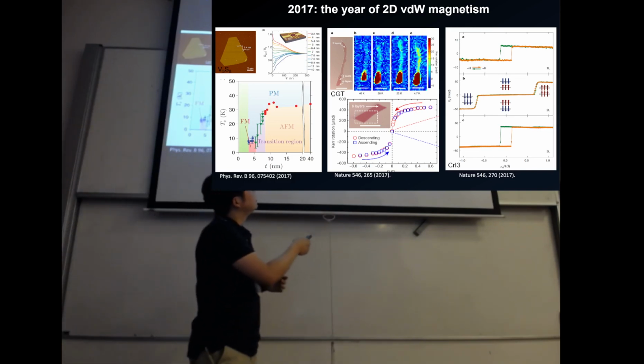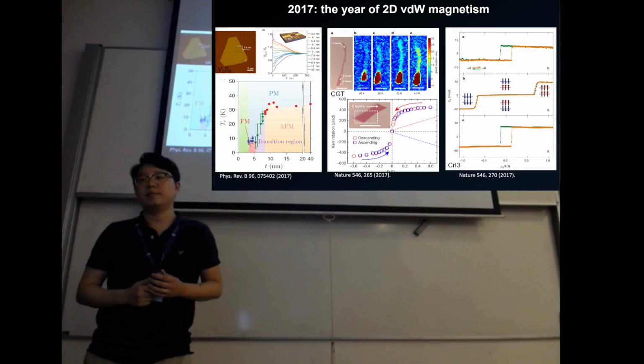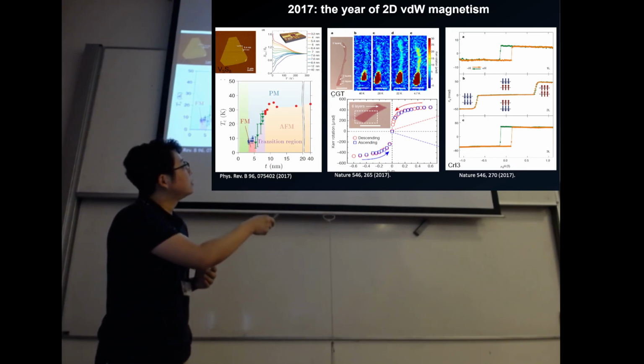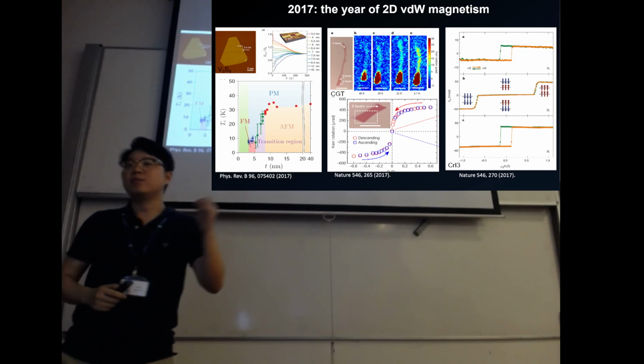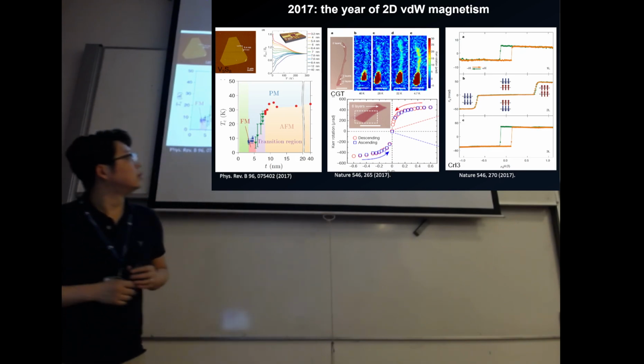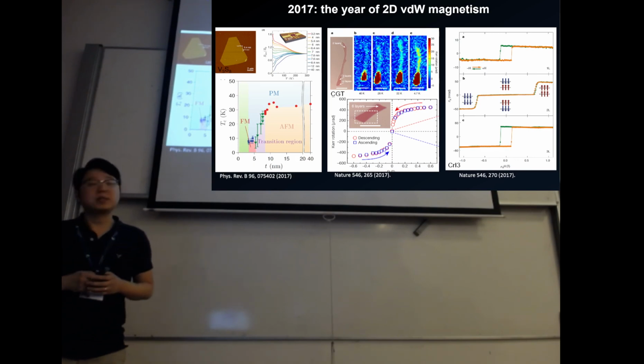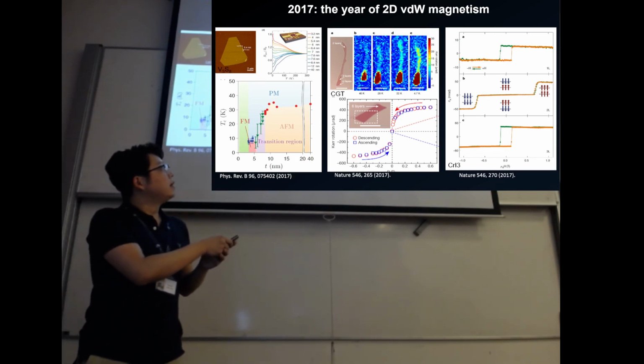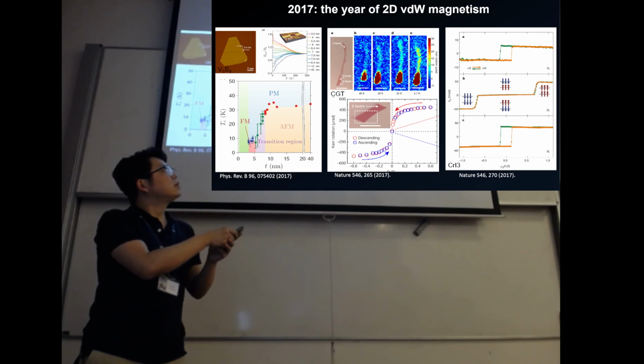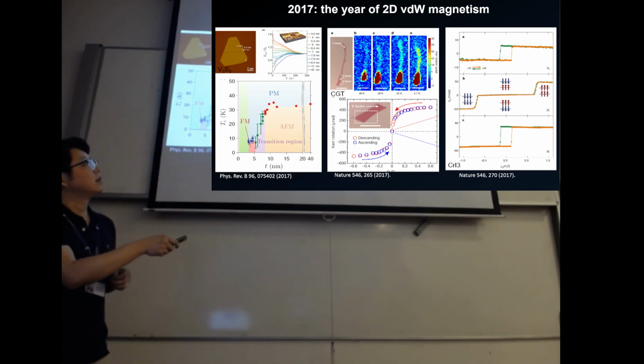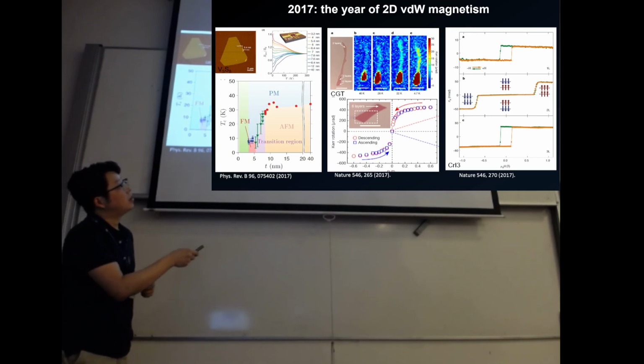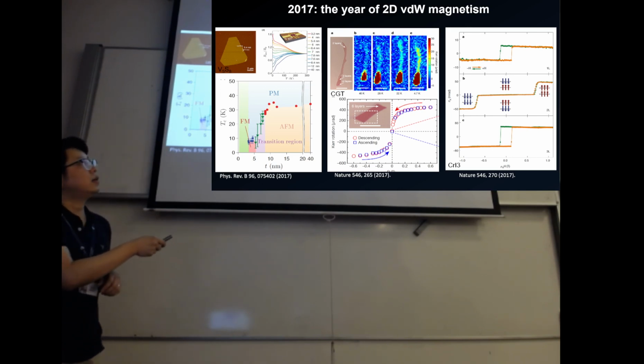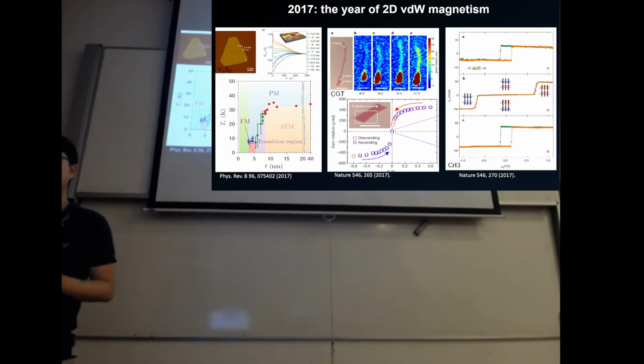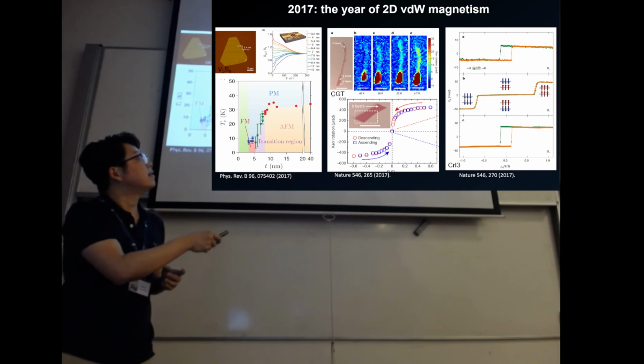And this compound, on the contrary, is a bilayer system that shows, at zero magnetic field, a zero net moment. This is the Kerr or RMCD measurement, which is optically probed. And at some magnetic field, one of the layers is flipped over and they all point up, so there is a net spin polarization at the positive magnetic field. On the other hand, the bottom layer flipped downwards, both are pointing down, so there is a negative moment. This is a typical anti-ferromagnetic behavior, and each of the layers is an Ising ferromagnet. So that's the single layer case, and that's the bilayer case.